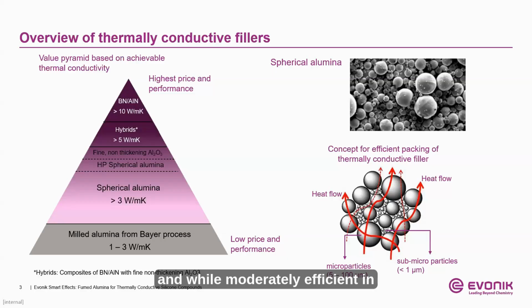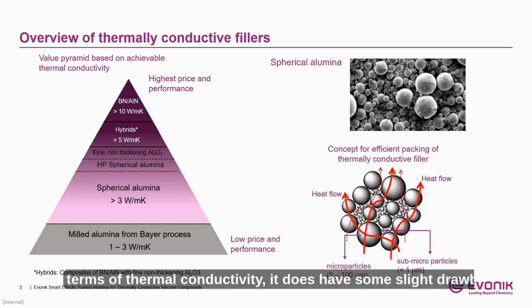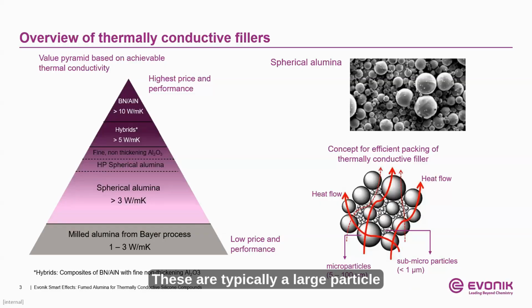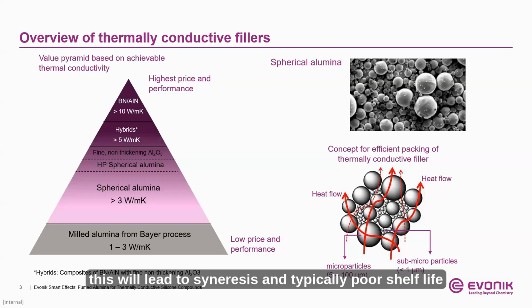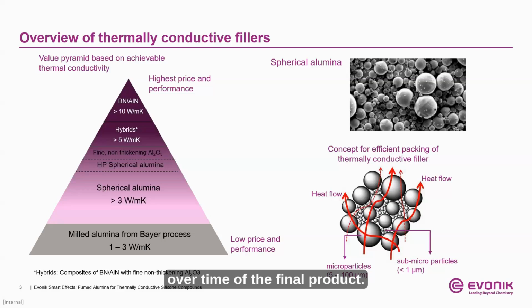And while moderately efficient in terms of thermal conductivity, it does have some slight drawbacks. These are typically a large particle size material, which tends to lead to settling of the spherical alumina when highly loaded in these adhesive systems, when used at the high concentrations needed to generate thermal conductivity. Again, this will lead to syneresis and typically poor shelf life over time of the final product.